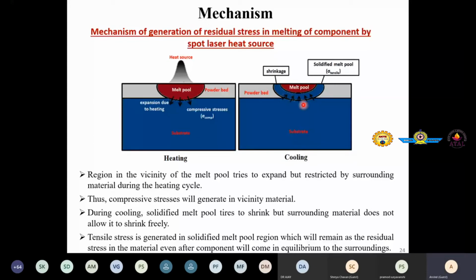When the laser moves away and that melt pool starts to resolidify, you can see very well that when shrinkage is happening, most of the metal shrinks, right? And because of that shrinkage, different kinds of stresses are developed near the melt pool. So you see, and this is experiencing a tensile stress.